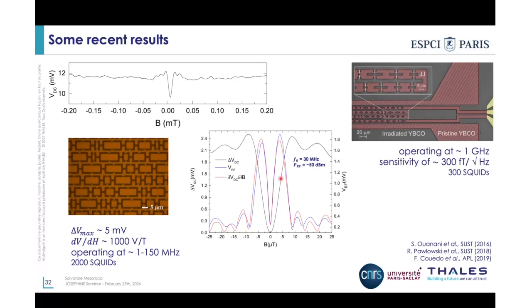But what is important to see here is how it actually conforms to what I showed you at the beginning, how we make a SQIF work as an antenna, because here you have in dark blue, in black, the SQIF. Okay, that's the voltage against magnetic field with the typical anti-peak behavior. And then whenever you plot also the output voltage seen at the output of the SQIF, whenever there's an electromagnetic wave sent into the SQIF with, for example, a power of minus 50 dBm and a frequency of 30 megahertz in this case, you see that the blue curve, so it's the voltage seen at the output of the SQIF, actually increases and reaches its maximum exactly where the SQIF has its maximum slope. So it actually is a way of tracking the derivative, which is the red curve, of the VH curve.